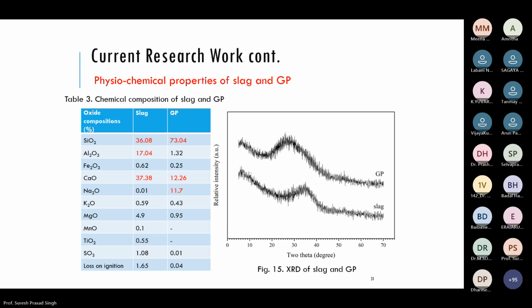So this is the composition of slag and GP, and you see that sodium oxide, 11%, is there in GP. So that reduces the consumption of sodium hydroxide that you use as an alkaline activator, because GP contains sodium oxide, sodium cations are there. And the release of silica is also more here, and it also contributes silicon ions for geopolymer production. So these are the two advantages of using GP along with fly ash or with slag and all these things.